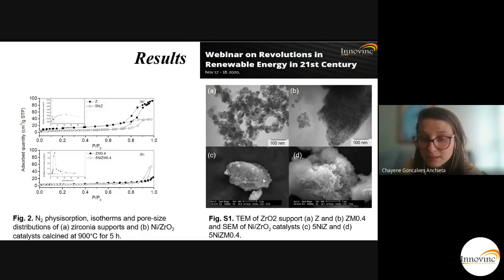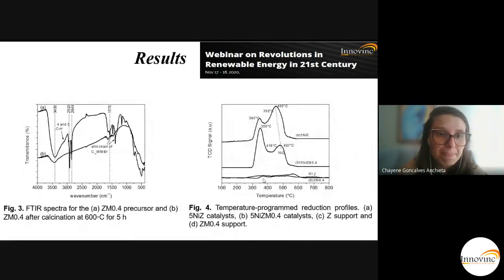Then here in the scanning electron microscopy, we can see that after adding the nickel, we have particles with different morphologies and with different characteristics when we compare each other. Now here we can see the nickel zirconia catalysts before and after the calcination, and we can see that we lost the ionic liquid, which means that we have only the catalytic activity of nickel zirconia material.